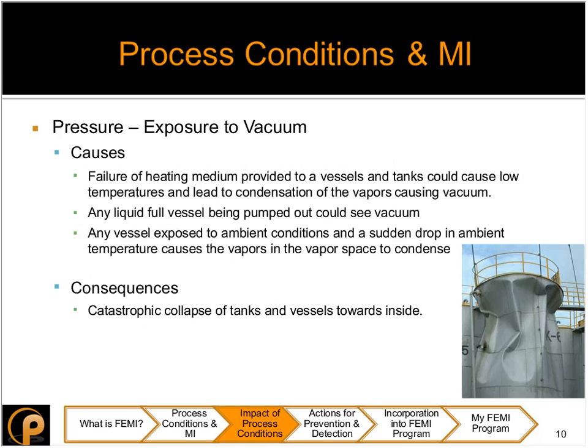Now the next scenario is exposure to vacuum. Exposure to vacuum can happen whenever there is failure of a heating medium to the vessels or tanks, which could cause low temperatures and lead to condensation of vapors, which results in a vacuum scenario. Another scenario where you can see vacuum is liquid-filled vessels. When they're being pumped out, you can see a vacuum scenario if your tank does not have adequate vacuum protection already designed in.